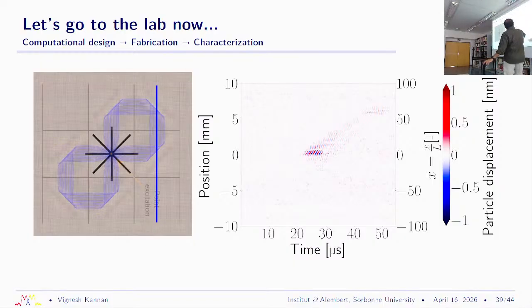The next thing to remember is, you see that the intensity of the wave is very, very weak compared to the previous line scans. And so we've really not looked at the intensity of the waves propagating through, because we are at a point where the experiments are still being done in air, in atmosphere, and you have a 2 micron layer between the device and the base layer. So now we're questioning if we need to do the experiment in vacuum, because you might have air damping and things like that. So the intensity is something that we're still figuring out, and this could be a direction where the intensity of the other wave was too weak for us to pick it up. In principle, it's linear elastic, so it should not matter much, but in the experiment we might have dissipation coming from elsewhere.